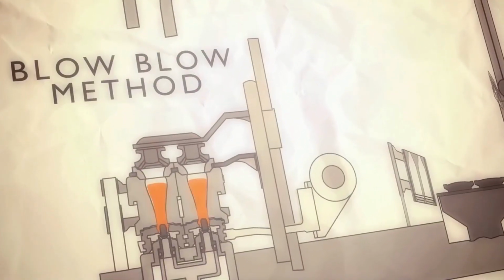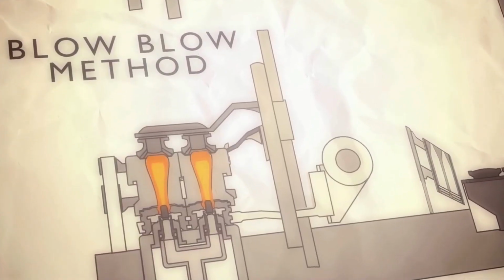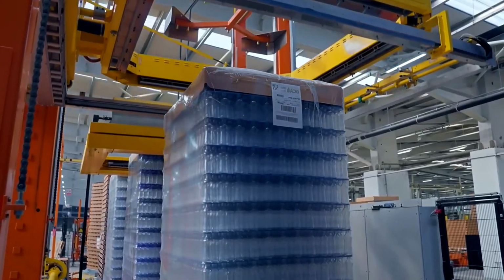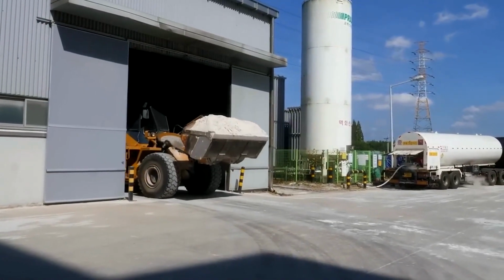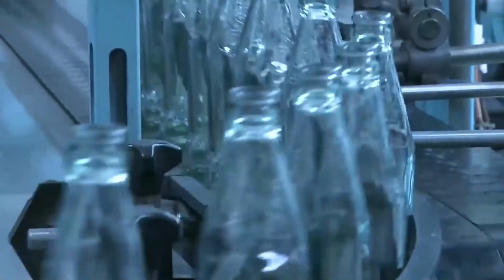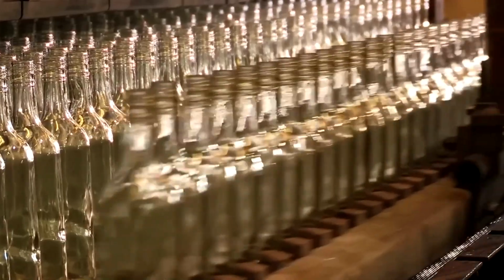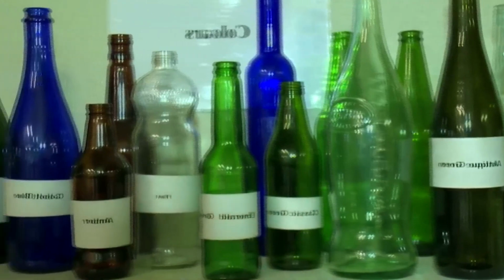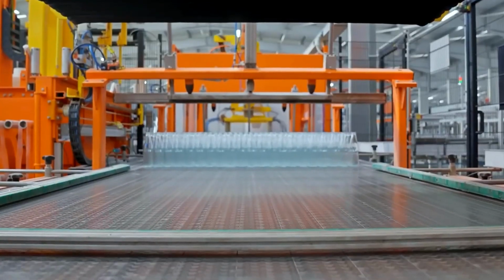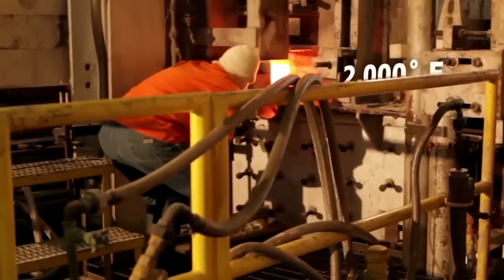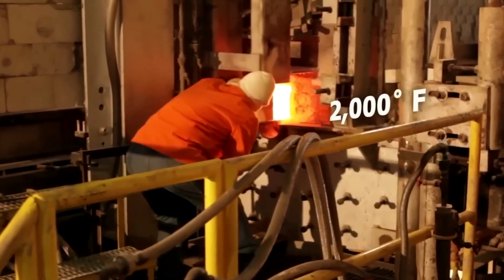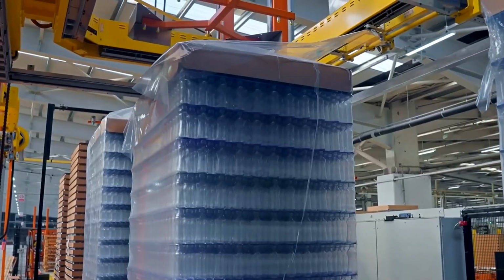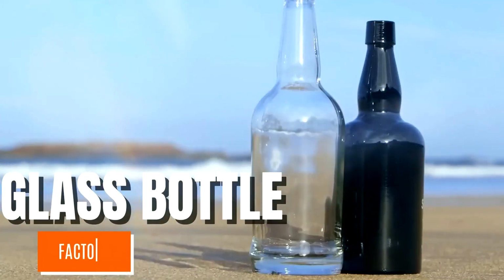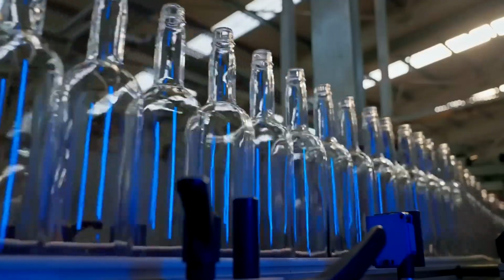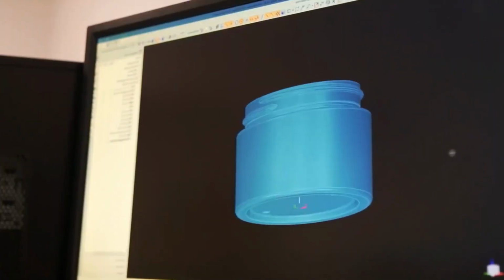Technicians, shielded from the immense heat, carefully oversee the process as the mixture is poured into special crucibles. Once the materials stabilize, each crucible's mouth is sealed, trapping the intense temperature to control the fusion. Within this inferno, workers must wear full fireproof suits and Kevlar gloves, as the ambient heat is a palpable, dangerous force. After 24 hours, the mixture is no longer sand, it flows like a river of fire.